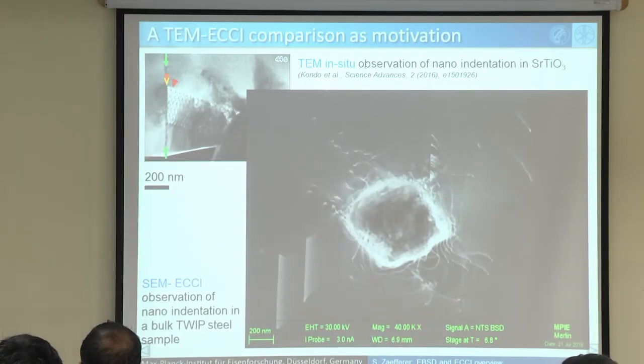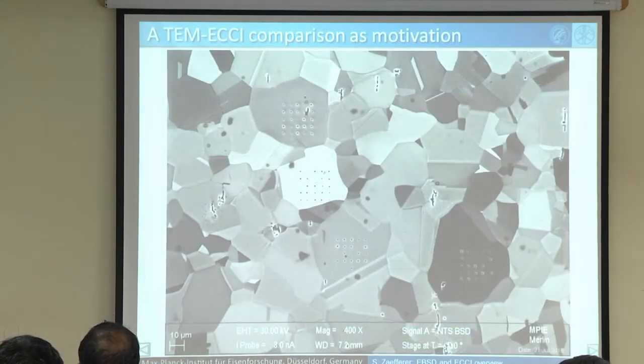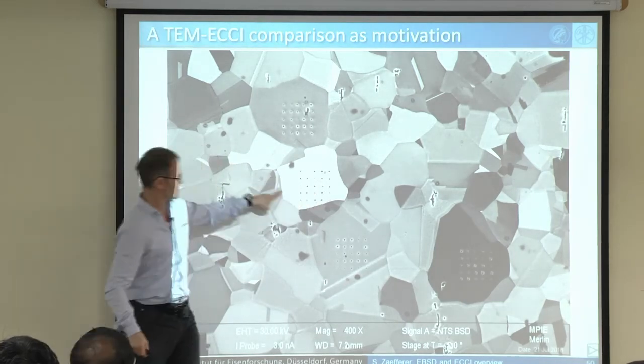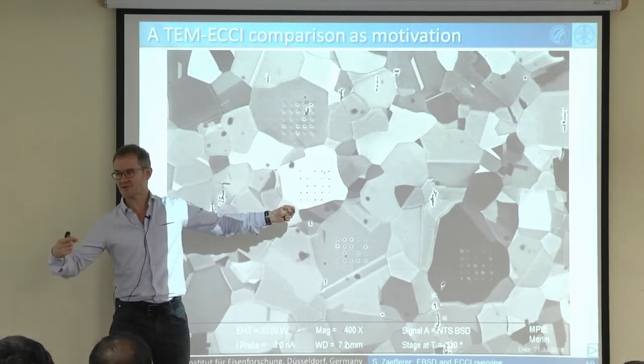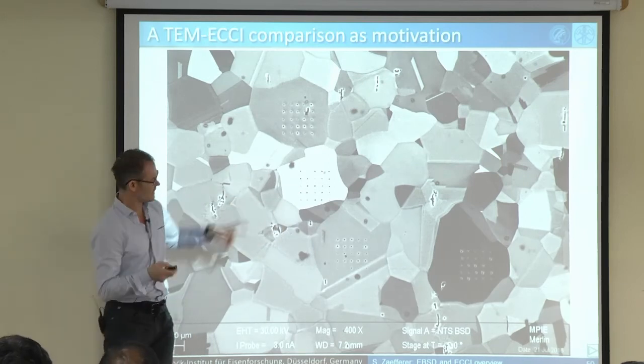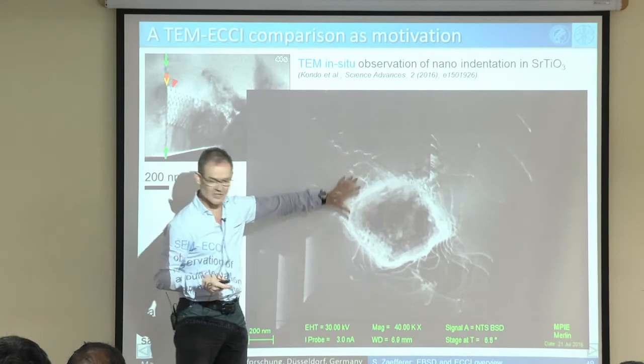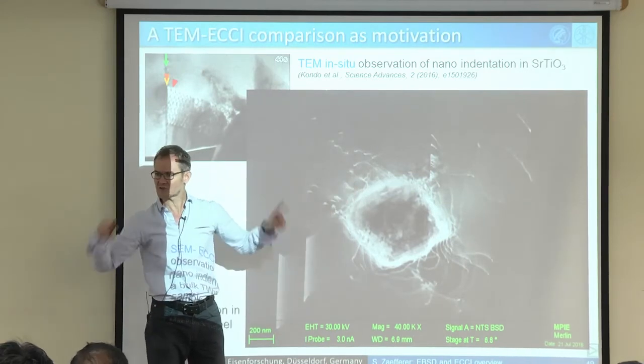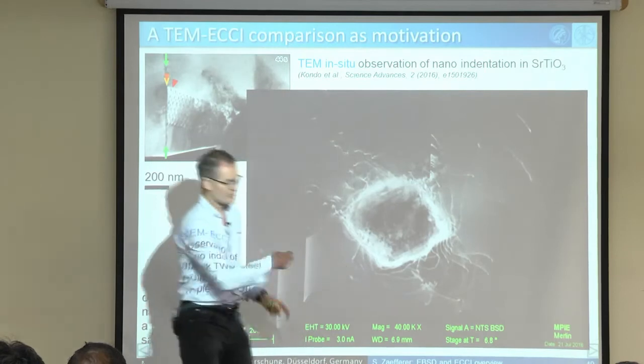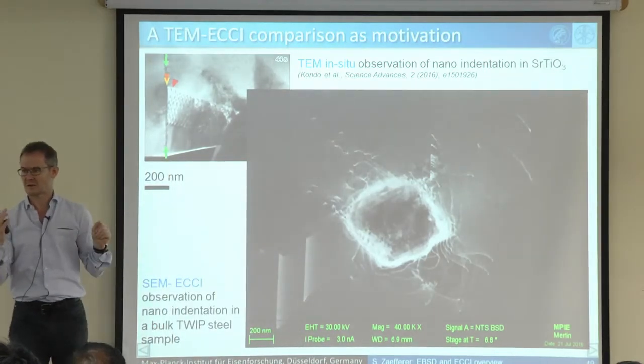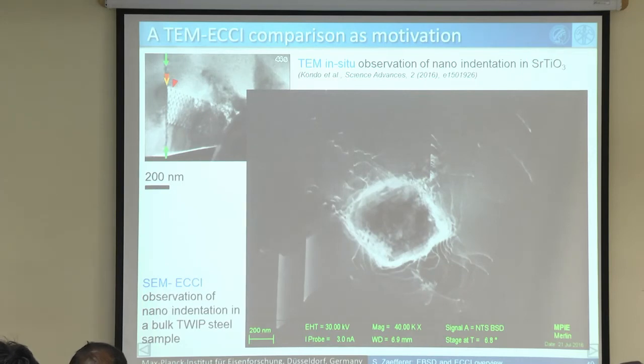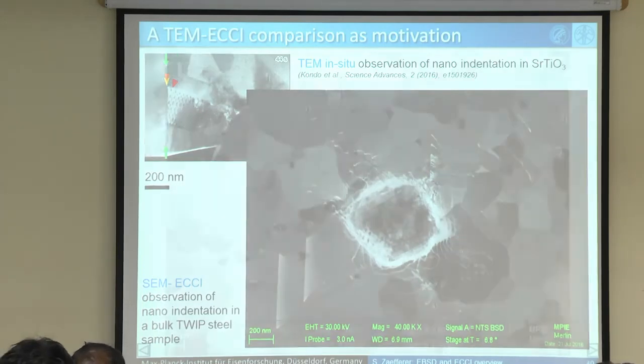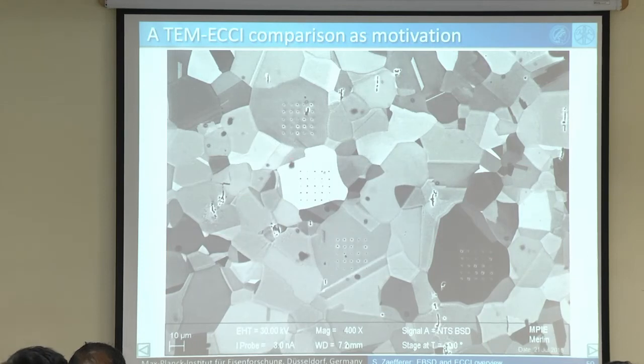And all this you can see very nicely, and this is an experiment which just takes a few minutes to make properly. And then you can say, now I can make this experiment not only on one grain, but on 100 grains, on all different kinds of orientations, which I measure with EBSD before. Each time I make a map of 5x5 indents, so I get statistics. By looking on 25 indents into the same grain, I can tell what of this is stochastic behavior and what is systematic behavior. So I can explore the systematics of deformation with this experiment, in different grains and different phases.